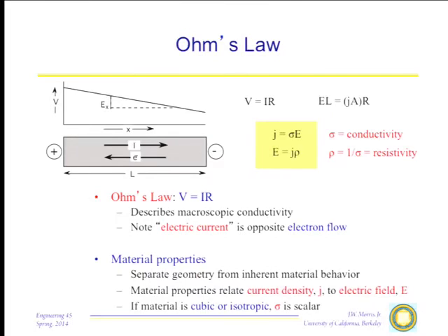Just keep in mind that if, for example, quite frequently these days, if you get involved in microelectronics, you might have conductive films that have hexagonal crystal structures. There you'll have to worry about two conductivities. The conductivity along the axis of the hexagon and the conductivity in the basal plane. So if you get to more complicated symmetries, you have to worry about more complicated vector versions of that law. We're not going to worry about that anymore here.